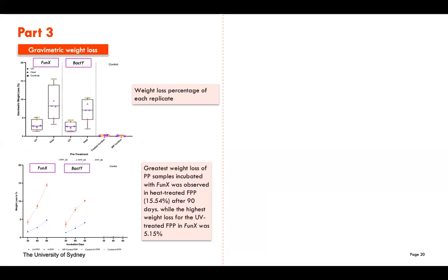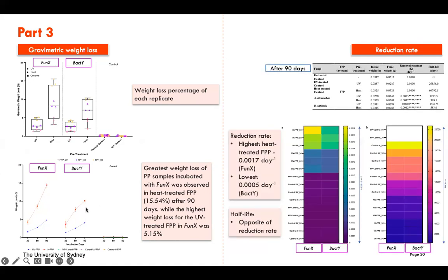We also did the same thing. We did weight loss determination because we also fed the polypropylene to this new isolate, and we see that this fungal isolate produces a higher weight loss percentage compared to bacterial isolates. You can also see the same trend here. We also calculated the reduction rate. Of course, it will be highest on the heat-treated samples, and the half-life will be the opposite. The control will never have any degradation occurring.